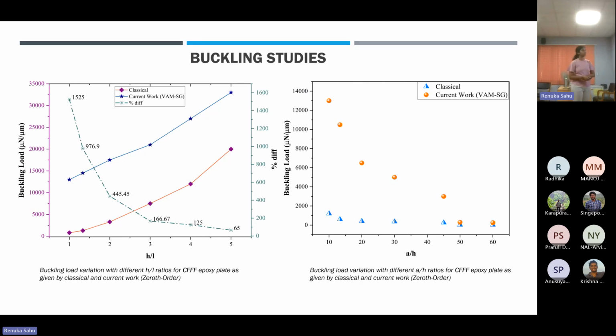We have also done buckling studies wherein we considered parameters like H by L, the variation with respect to thickness and material length scale parameter ratio, and variation with different beam plate width and thickness ratios. Here we can see for zeroth order how the buckling load varies as we increase the plate thickness.